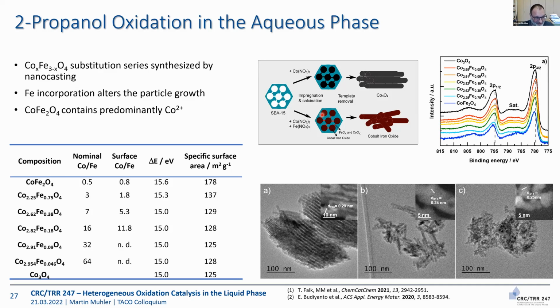Here we used different samples that were made by nanocasting, that is Eko Budianto in Harun Tüysüz's group at Max-Planck-Institut für Kohlenforschung, the Schüth department. And this is done by hard templating. That means we get nanorods because the template had straight pores. These pores are filled, the template is removed, and we get again high surface area, not nanoparticles now, but nanorods. And this data set was highly valuable because here Eko Budianto incorporated just tiny amounts of iron.